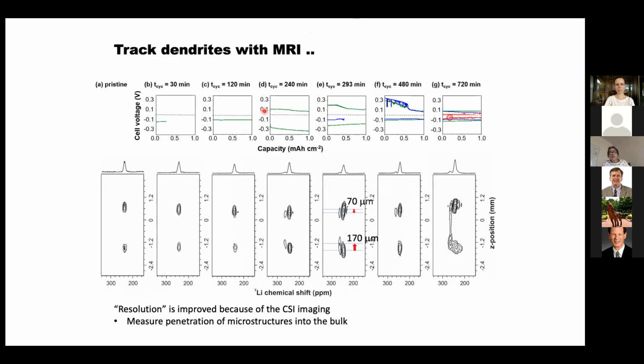You can use these methods now to understand and correlate the electrochemistry with the progression of the dendrites into these pellets without having to do cross sections and be destructive. So you can take a thick pellet where you've got a large overpotential, and then once the dendrites or moss start growing into it, the overpotential decreases because it's a shorter distance that the lithium has to travel. Then you get these signatures of short circuits. And when you start to see the whole lithium signal going from one side, then you've really got failure of the cell and short circuits.